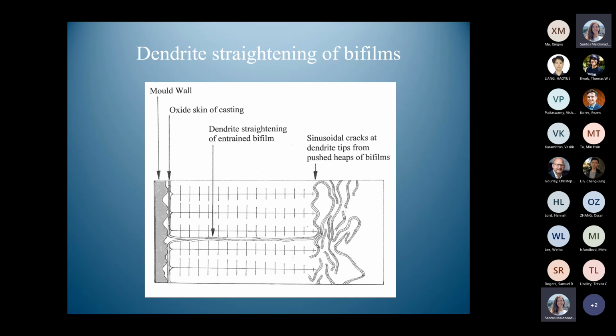And this is the kind of thing we see here. So some of the cracks have been flattened, and this, for instance, is how we see facets. Very often in the fracture surface of a casting, you get a kind of facet, and this is very common. So this is a kind of facet formation, and here we've got a kind of sine wave, which again you see on some fracture surfaces. And here you've got a complete mess of films that are still being pushed ahead in a heap.